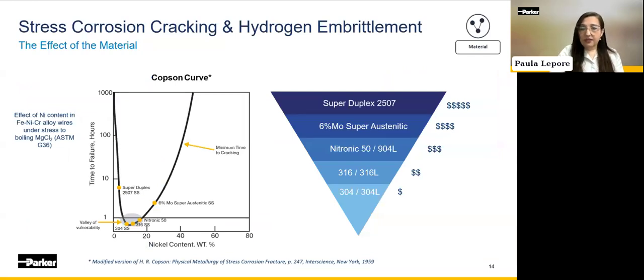One other interesting way to look at the material is how should we select the proper alloy based on its nickel content. Here you see the Copson curve and the stress corrosion cracking valley of susceptibility. This curve plots the effect of nickel content in a Fe-Ni-Cr alloy coupons under stress, subjected to a boiling magnesium chloride solution, or simply the ASTM G36 testing. The Copson curve shows in the very bottom there more susceptible materials to stress corrosion cracking, such as 304, 316, 316L. On the right side of the curve, the content of nickel that actually has a positive effect to the stress corrosion cracking resistance,